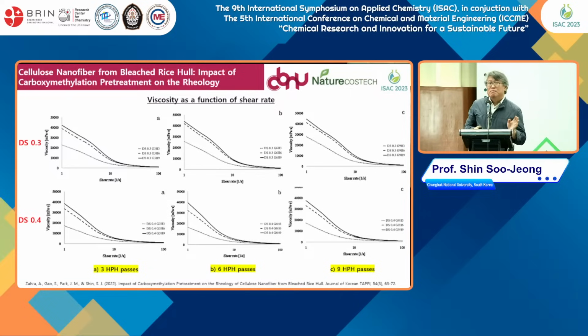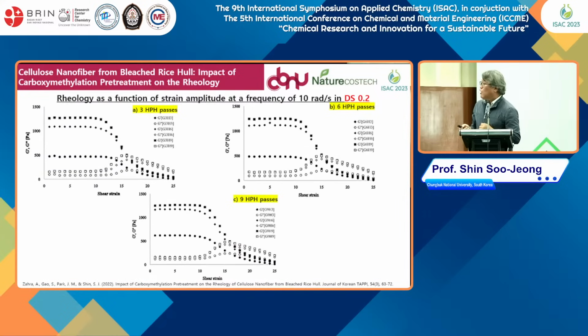Other research groups, from DS.1, report that increasing the DS means decreasing the size of the nanofibril, and increasing viscosity means increasing the DS. But based on our research group, this viscosity goes up and down around DS.5 or 0.4. It's depending on the amount of mechanical treatment.